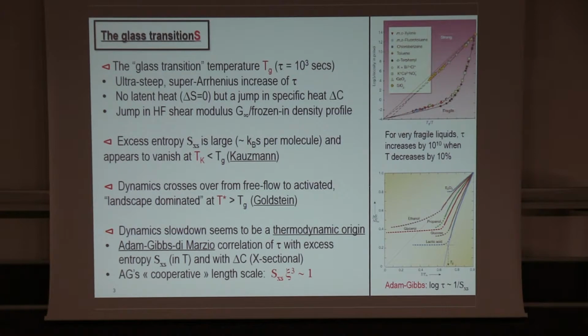And finally, something that's not really experimental, but there was this suggestive idea of Adam-Gibbs that there must be a cooperative length scale accompanying this slowdown. And I always found the argument pretty woolly, but essentially it says that this cooperative length scale must be such that there's at least one state to relax to on that scale. So the excess entropy times the cube of this length has to be something that's over 1. Okay, so that's essentially the challenge that was to be explained back then.